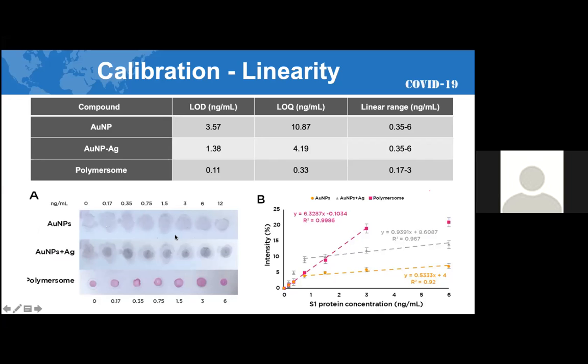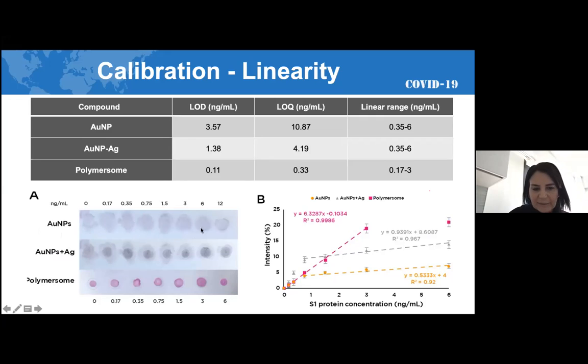These data are not so visible, but you can see our dot blot assay with gold nanoparticles. After reagent treatments, darker spots are obtained, more stable and darker spots, and polymersomes. So, plot calibration, and as you can see, polymersomes provide better linear plots in comparison with the others. So this is the reason why we continue with this structure instead of gold nanoparticles. Also, of course, gold nanoparticle plus the hydroquinone silver nitrate reagent is better, but since we can tune polymersome features, we continue to use polymersomes.